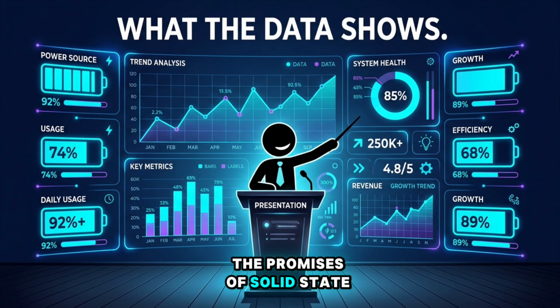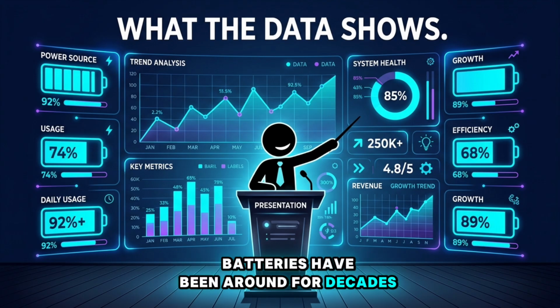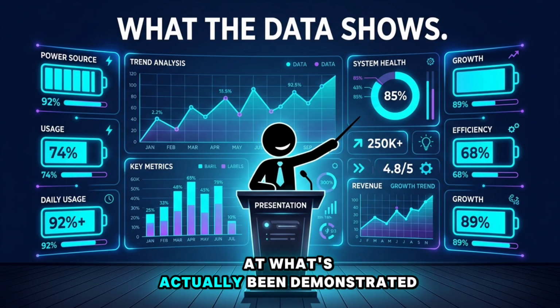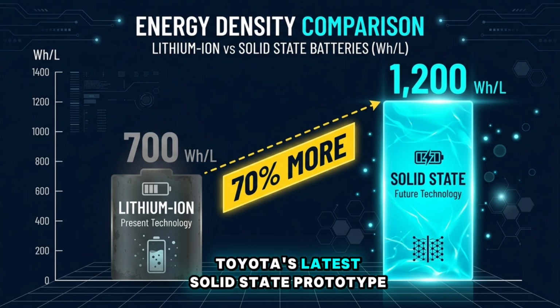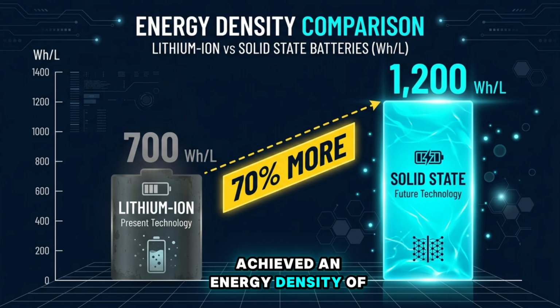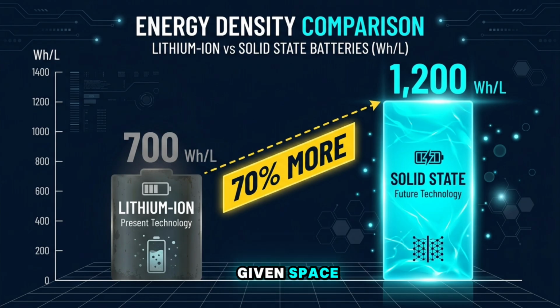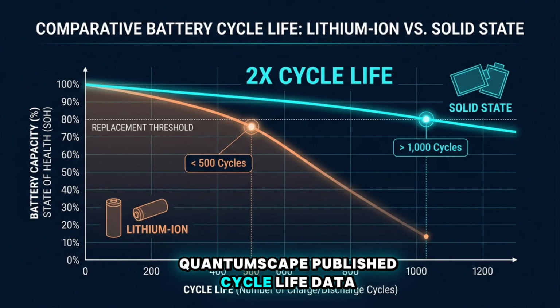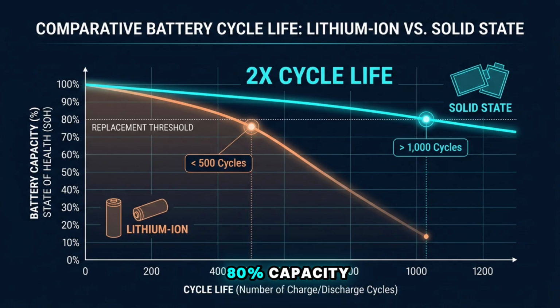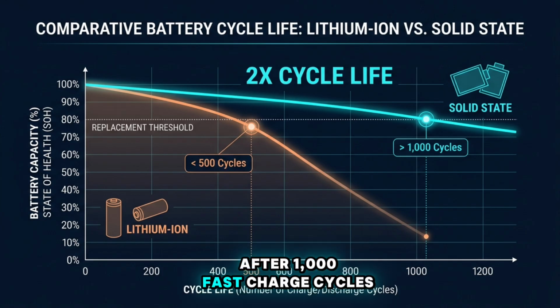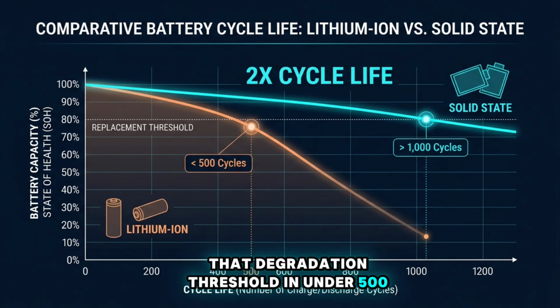The promises of solid-state batteries have been around for decades, but promises don't power cities. Data does. So let's look at what's actually been demonstrated. Toyota's latest solid-state prototype achieved an energy density of 1,200 watt-hours per liter. Current lithium-ion tops out at around 700. That's a 70% improvement in how much energy fits in a given space. QuantumScape published cycle life data showing their cells retaining over 80% capacity after 1,000 fast charge cycles. Most lithium-ion cells hit that degradation threshold in under 500.